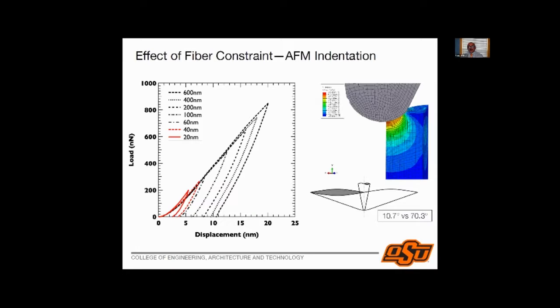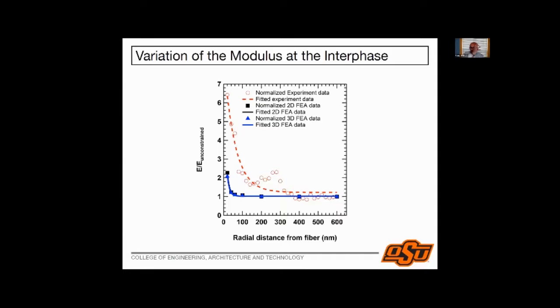So if I look at the slope of the unloading curve, this is from finite elements, the unloading curves are all the same. That makes sense, because you have the same material, but you don't have any constraint effects. You start seeing constraint effects only when you start coming very close to the fiber. So we took the finite element work and we took our experimental work and combined both of them, and this is the combined result, and this basically explains to us what is going on.